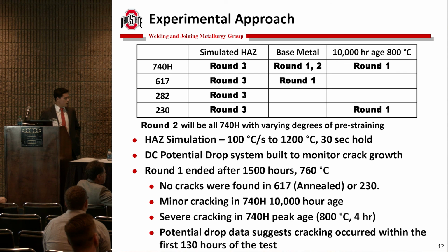So there was no cracking in a couple of the alloys which start out without any precipitates. There was minor cracking in this 740H, which had been aged for 10,000 hours. And there's some pretty severe cracking in this 740H base metal sample. And you will see why. So the problem, though, and the motivation for making round two have reduced pre-straining at lower temperatures, is that I think all the cracking occurred sometime within the first 130 hours. And I'm not real sure about that because I spent those first 130 hours tweaking this and that in the potential drop system.